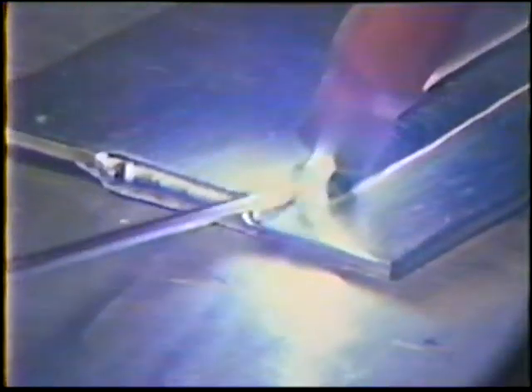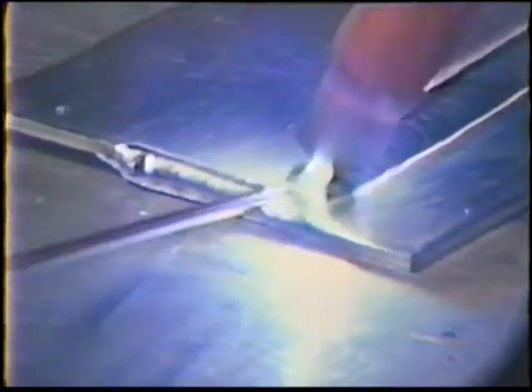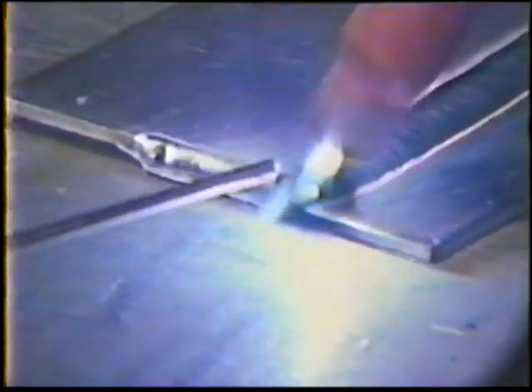Dip the filler rod in and out of the leading edge of the puddle without touching the rod to the tungsten. When the puddle appears as a half-moon shape, add filler metal to fill the gap. Oxide removal is indicated by a white area appearing ahead of the arc. At completion of the weld, decrease the amperage while filling the crater. Hold the torch in position to post-purge the weld.